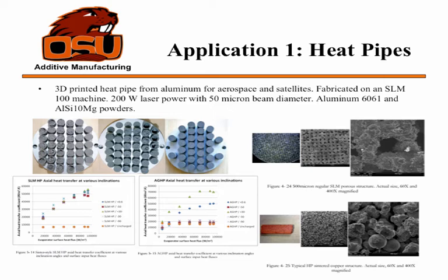And then I also compared it to a traditionally manufactured axial groove heat pipe, and you can see there's only two orientations, the triangles and the diamonds, which are 0 degrees and 30 degrees, that actually perform well. All the others that are more vertical orientation, they actually don't have good heat transport at all. That's uncharged, so that means it doesn't have working fluid in it. So that's the heat transport just from the structure, not from the actual evaporation transportation.